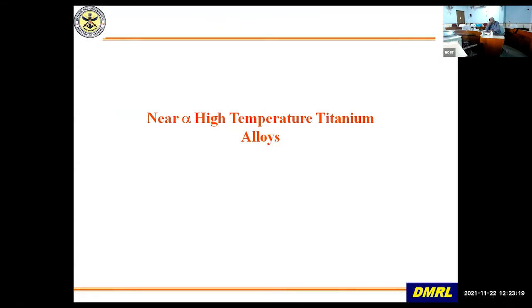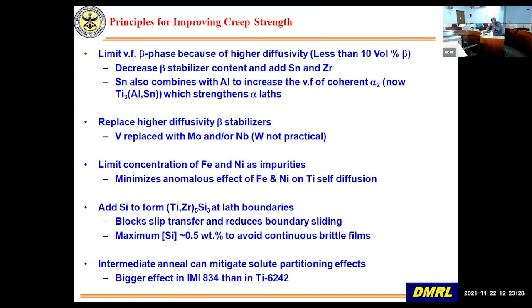Now coming to near alpha high temperature titanium alloys, because these exist toward the left hand side of the alpha plus beta phase diagram. Now, what is the design philosophy for high temperature? We are mainly looking for creep and oxidation resistance. So what you have to do is basically limit the beta phase volume fraction, because as I told you, beta phase, because it is BCC, the diffusivities are higher. So you have worse creep properties. So you have to decrease the beta phase content. So it is normally kept less than 10 volume percent. So that is why you have to have lower beta stabilizer content.